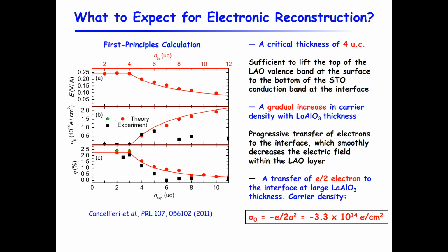And if that happens, what you can expect is that you will need 4 unit cells of critical thickness before this transfer takes place. You have to offset these band gaps so that you can have the transfer. And after that, you will have a gradual increase of the carrier density. Eventually, you would have the transfer of half an electron, which translates into 3.3 times 10 to the 14th electrons per centimeter squared at larger thickness. So how much electron is transferred to the interface depends on the thickness. Right?